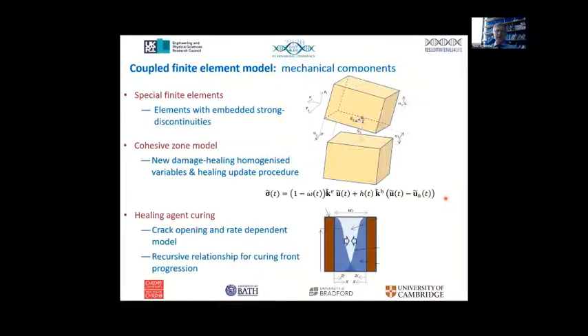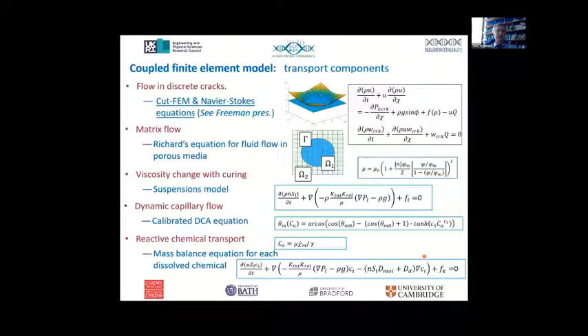And the curing front model, where we have learned how curing takes place, and we actually track this developing curing front, and then when solid material percolates across the crack, that's when healing is detected. And by taking this approach, we've been naturally able to simulate crack opening dependency, crack rate dependency. Okay, what a full slide.